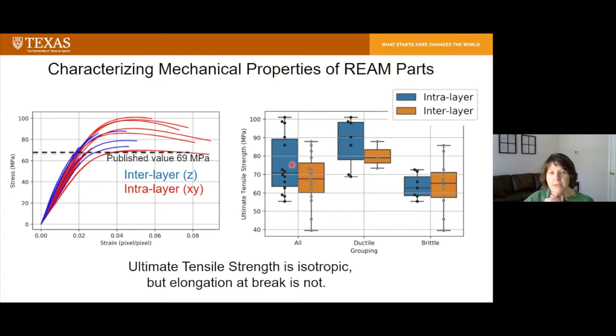On the right here, you can see box plots of the strength values for all of the specimens, intra and interlayer. One of the things you'll notice is that the means of those two sets are very similar. So there's no statistically significant difference between strength within the layer or across the layer. That means that we are not observing significant anisotropy in these parts. They're fairly isotropic. But elongation at break, on the other hand, is not. You can see that visually from the plot on the left, but we've run the statistics as well, and there is a statistically significant difference in elongation at break.